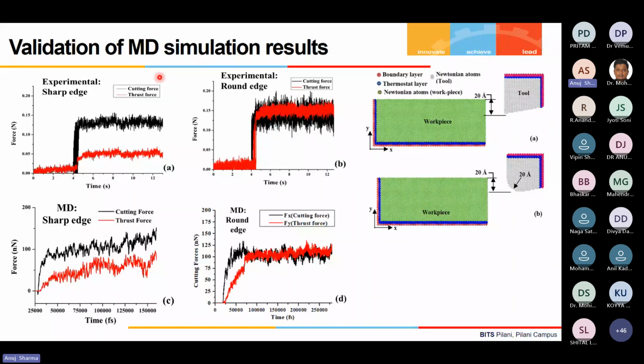Since we run the simulation, the first thing we have to do is validate the simulation results. We cannot make a one-to-one comparison because this is taking place at nanoscale, and in our experiments the tool and workpiece are usually large. Only the cutting zone is small, but the tool and workpiece are very large. So we have to find a way to validate these results. What I did was take one sharp tool and one round edge tool and evaluate their forces when the cutting took place. So for the sharp edge, there is the MD simulation and there are the experimental results.